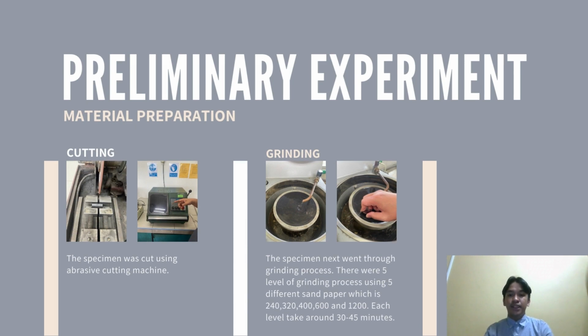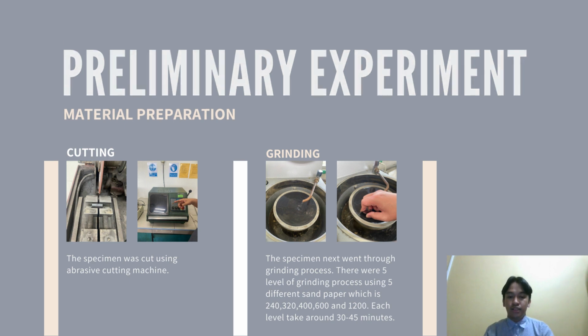Next, for the preliminary experiment that I have carried out during this FYP1, before carrying out the experiments such as microstructure analysis and hardness test, I have to do material preparation of the specimen. The first process of material preparation is cutting. The specimen was cut using an abrasive cutting machine. The next process is grinding. The specimen next went through the grinding process. There were 5 levels of grinding using 5 different sandpapers, which are 240, 320, 400, 600, and 1200. Each level takes around 30 to 45 minutes.